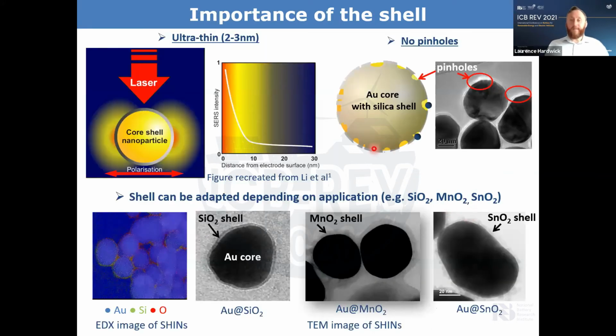One of the important things about the shell is that it has to be of a certain thickness. If it's too thin, then you're going to get pinholes, and so you're going to get the information primarily of adsorbates on these pinholes in the silica shell. If you have it too thick, then you're not going to get any enhancement at all. Here we have a simple graph showing the relationship of the surface enhancement intensity with the distance from the electrode surface. There's a sweet spot where we can avoid having pinholes and still have a suitable enhancement, and this is around 2 to 3 nanometers thick of a silica shell that can be put on the surface.